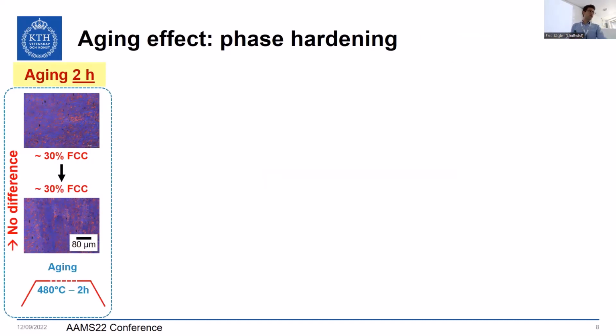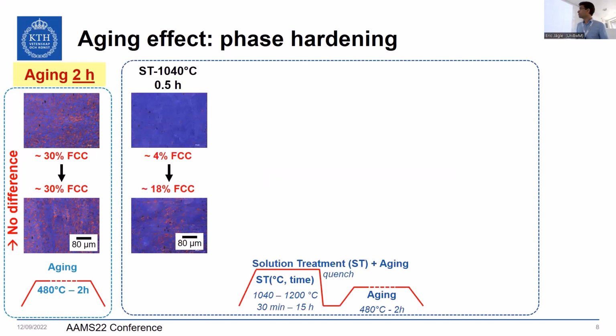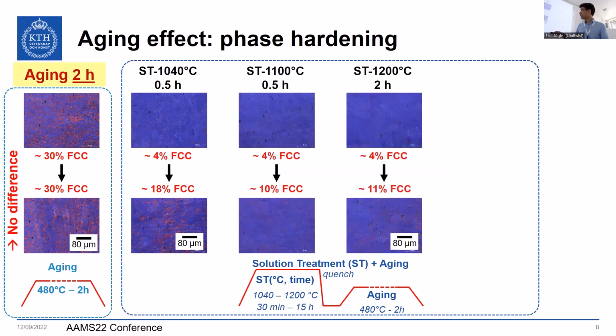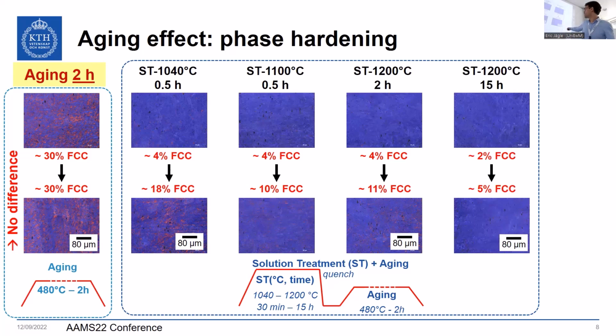So we will show on this slide aging performed after 2 hours, and we'll see just after that why I picked this 2 hours aging. From the as-built materials, there's mostly not much happening in terms of phase transformation. However, if we look at the solution-treated alloys, then after aging of the 1040 degrees C, half an hour, we have an increase of the FCC phase to 18% at the end of the aging, 2 hour aging at 480. And it's decreasing with the solution treatment, 10% for those two. And for the last one, we have 5%